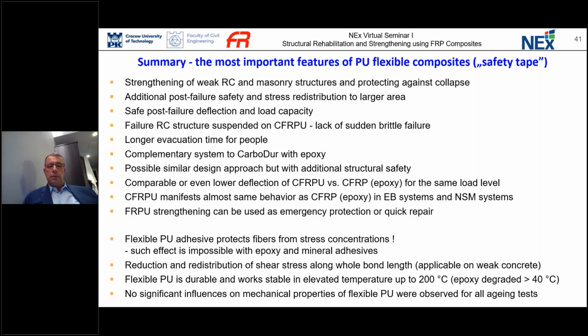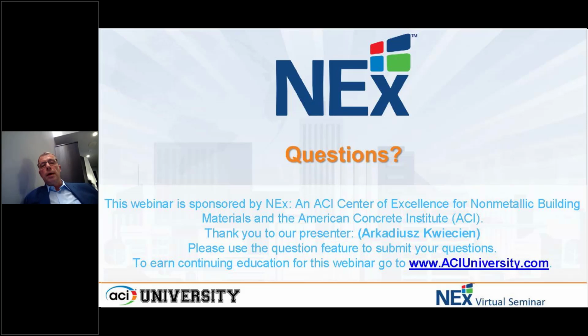of the weak substrate. Additionally, I would like to point out that this kind of flexible polyurethane is resistant to high temperature, I mean up to 200 Celsius degrees, so it can work at elevated temperatures, instead of epoxy resin that starts to degrade over 40 Celsius degrees. And also during aging tests, we did not find significant influence on mechanical properties of flexible polyurethanes. So thank you very much. I am happy to answer questions.